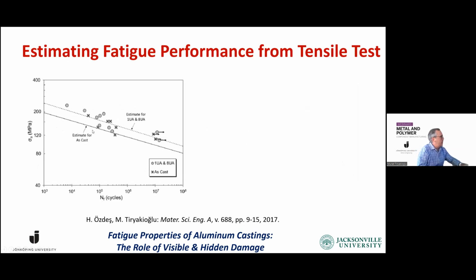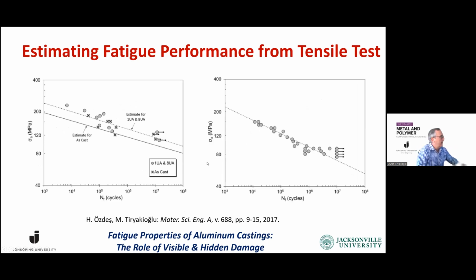We could estimate, with a little bit of underestimation, for the as-cast. The estimate is better for the underaged and overaged alloy. And here the estimate is pretty good. At a certain point, it's supposed to make a bend, but we did not expand it that far. So this is where we stopped. Obviously, it can be further developed.